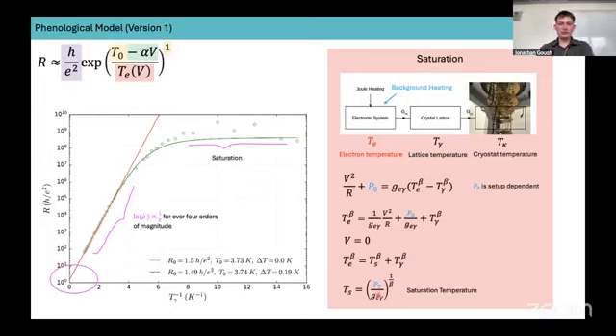You can also do things like improve the noise levels of your fridge. Recently, we removed RF lines that we think were adding noise to our experimental system, and we found that the saturation temperature of these samples decreased as this P0 value got smaller.